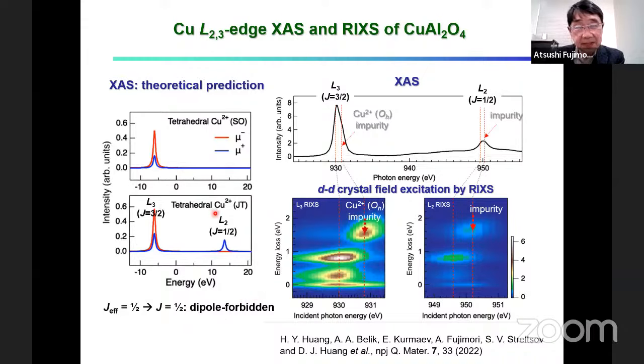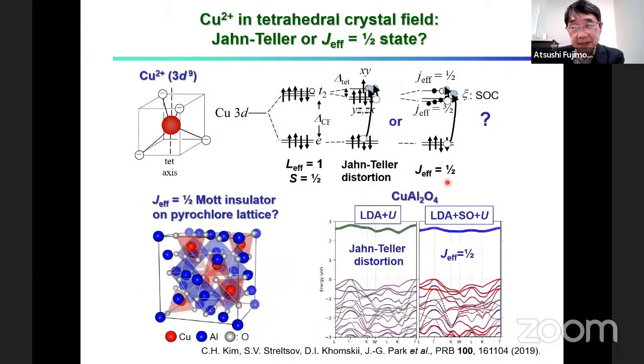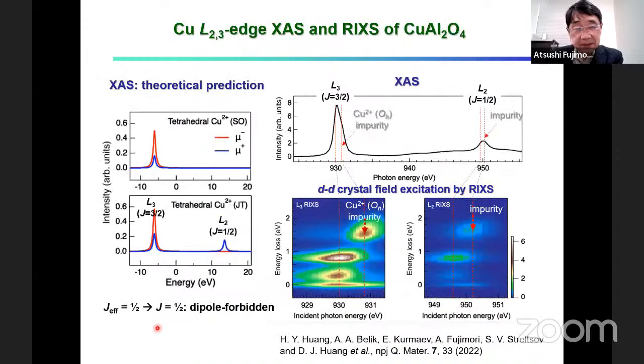X-ray absorption spectroscopy. X-ray absorption is of the 2p core level, which is split into L3 and L2, J equal 3/2 and 1/2. But if the ground state is J effective 1/2, then transition of the core hole to this J 1/2 is forbidden. So the X-ray absorption spectra will miss the L2 component. Actually, real materials have 2 components, because this is a very difficult material and there is impurity, copper 2 plus ion in an octahedral site, which may be overlapping.